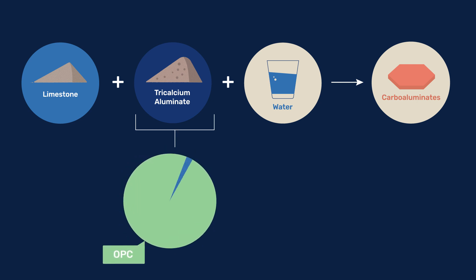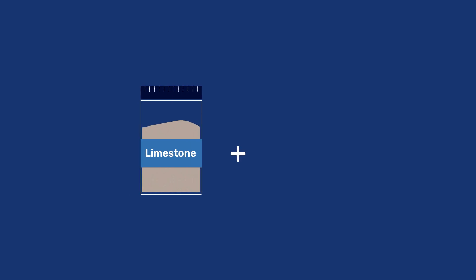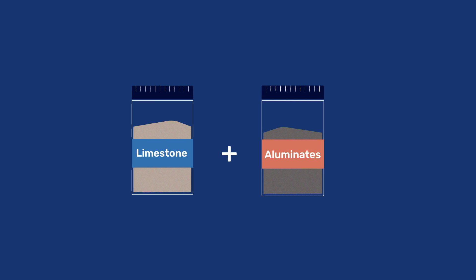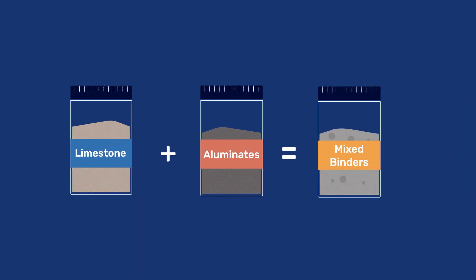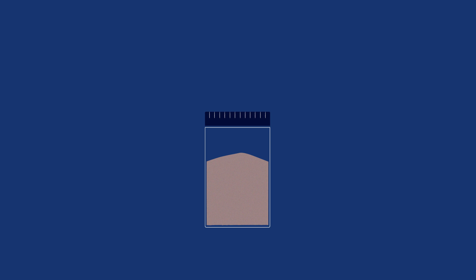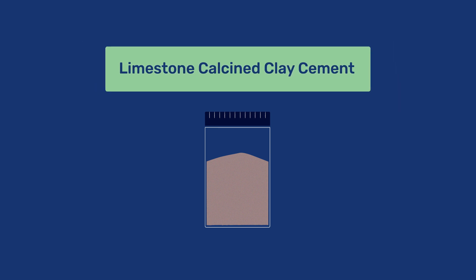The fact that limestone can react with aluminates to produce useful binding phases, but that OPC contains only limited amounts of them, calls for adding, alongside the limestone, SCMs that contain a fair amount of aluminates. This brings us to mixed binders, which in European norms include an M labeling along with an identification of the SCMs used. An example of rising interest is the limestone calcined clay cement, termed LC3, which is the object of a separate video.